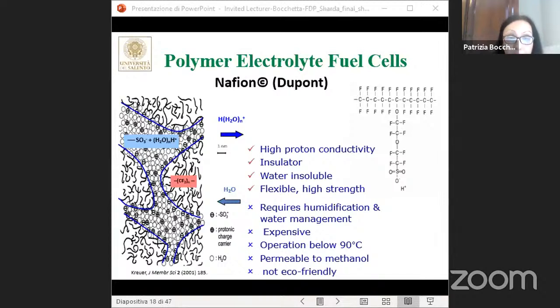The most famous and also the first developed polymer for fuel cell was commercialized by DuPont with the trade name of Nafion. Nafion has almost all the necessary properties to be a good fuel cell membrane. It's composed of a perfluorinated backbone with side chains that are terminated by strong acid sulfonic groups. So the resulting membrane has a semi-crystalline structure, which allows mechanical stability, and high ionic conductivity provided by the strongly hydrophilic terminal side chains and the sulfonic functional groups.